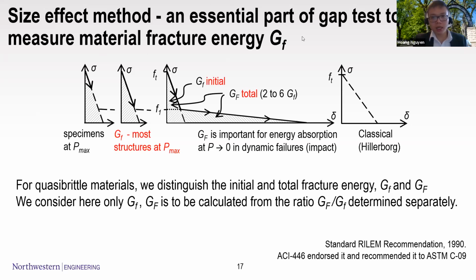So the size effect method is a method to measure the fracture energy of materials. And this fracture energy corresponds to the initial part of the cohesive law for one material point. So for example, if you use a cohesive model and you implement the bilinear curve for the cohesive layers, the size effect will give you the energy of the initial part only. And this is the most important part, because the later part will happen when you have a very big separation and the material should allow a very big opening. And at that stage, the load measured is far in the tail already.